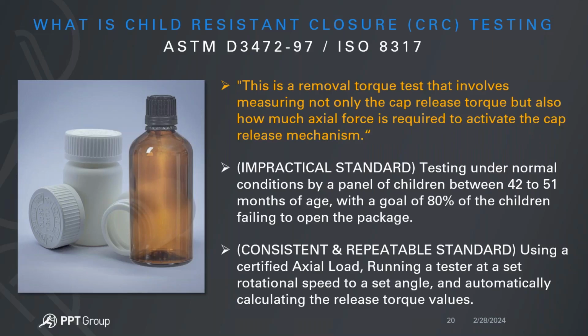So yes, that's still probably a test that people do, but if you're able to establish a more consistent and repeatable standard using a certified axial load, running the tester at a set rotational speed to a set angle, and then having the software automatically calculate the release torque values, you are in a more reliable testing environment, and you'll generate results that you can actually trust, as opposed to the more subjective test of using real-life subjects, or children in this case.